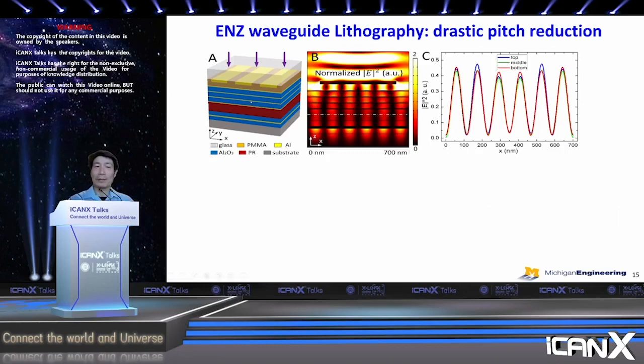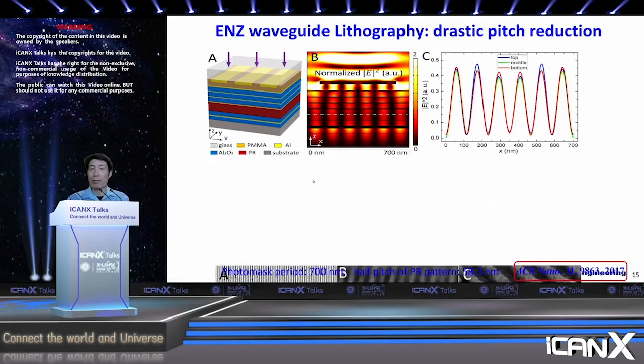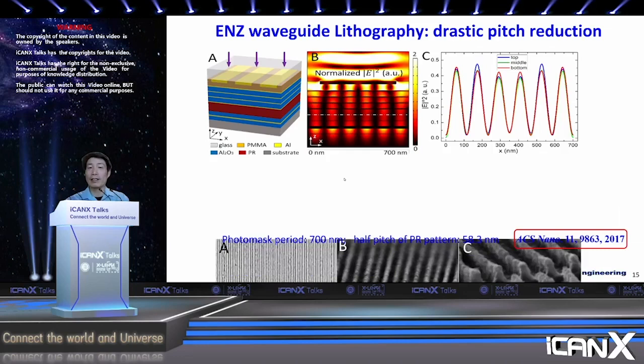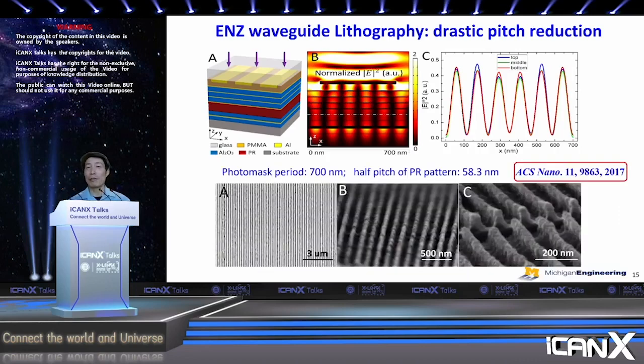And the nice feature about this is not only can you form these periodic patterns, but now we can use a much larger period. We can use higher order diffraction and let them interfere to create much smaller period patterns. This is an experimental result. Now the photomask period is 700 nanometer, much easier to make. We can still get a pattern feature size less than 60 nanometer with a very decent aspect ratio. This is another ACS Nano paper. So this makes it much easier to do in practice.